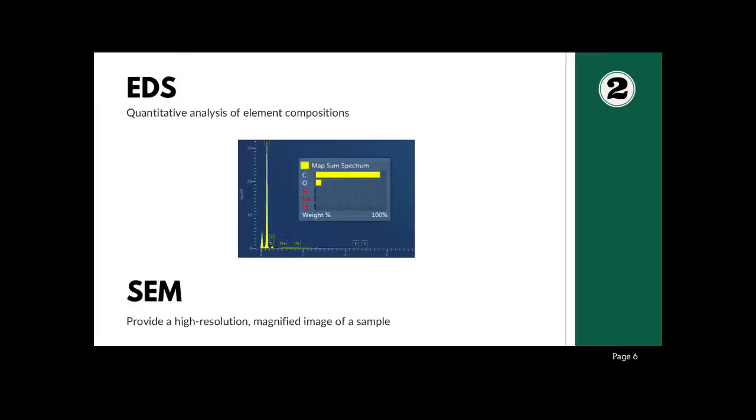Since our microscope also has a function of EDS, which can tell the composition of any elements in the sample, we can report that our adsorbent consists of carbon, oxygen, silicon, and titanium. However, the exact proportion of each element is not confirmed, due to the fact that we use carbon tape for gluing the sample to the tool, making the figures vastly overestimated.